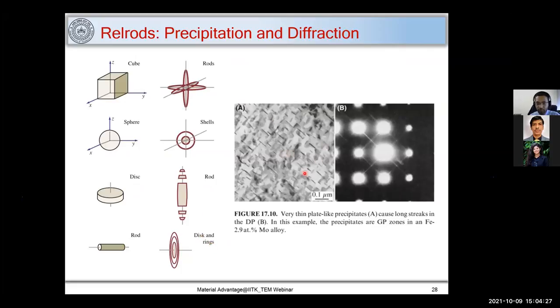Let's focus on this image now. You have these precipitates or GP zones in the microstructure. And these precipitates are in this direction. So you get rel rods, or streaking, in this direction. So the rel rod will be in this direction and streaking will be in this direction. And there are some other precipitates which are in this direction. So you get streaking in this direction. So when there is streaking present in a material or in a micrograph, you can clearly say that there are some fine precipitates, and you can find out their locations too.